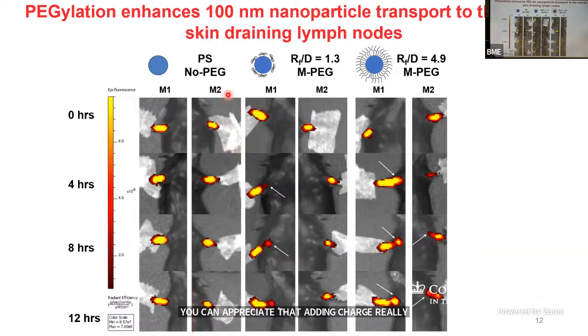And so you can appreciate here, these are just some examples. With the non-PEGylated particles, you really don't see anything going to the lymph node. When you have the intermediate PEG density, you do start seeing, in some cases, the particles accumulating in the lymph node. For some reason, it's not always the case, and it's not as much as when you have the densely PEGylated particles. So that little dot that lights up, that's basically the lymph node that's in the armpit of the mouse.